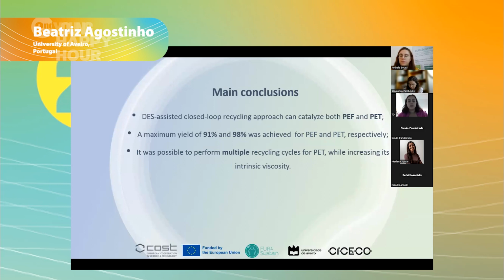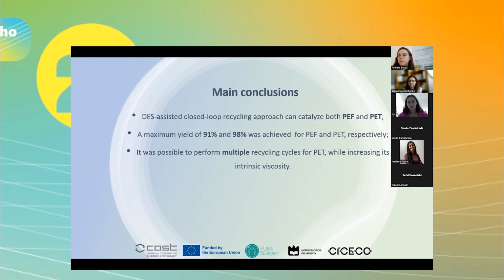As for the main conclusions, we saw that this DES-assisted closed-loop recycling can catalyze both PEF and PET. We reached a maximum yield of around 91% for PEF and 98% for PET when we added the DBT, and it was also possible to perform multiple recycling cycles while increasing slightly the intrinsic viscosity.